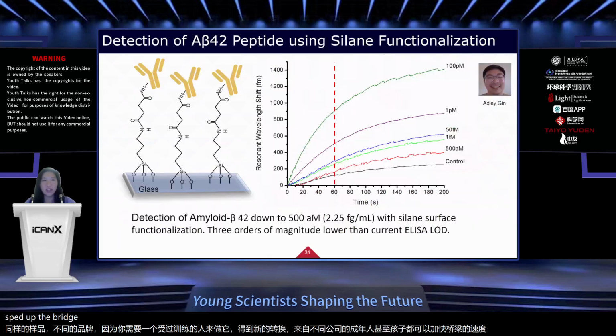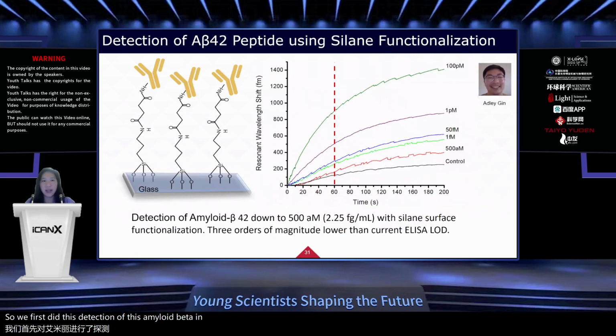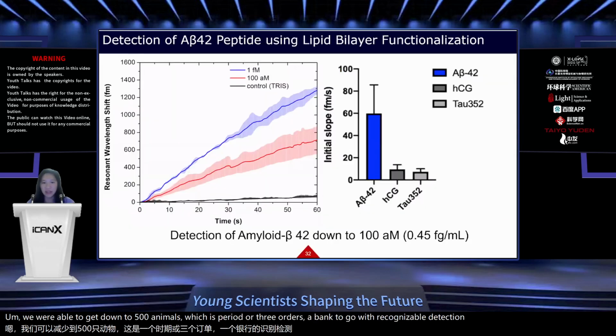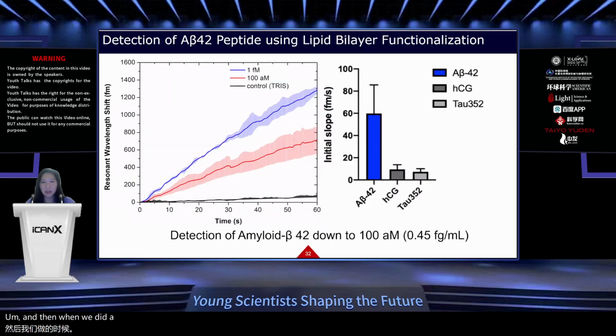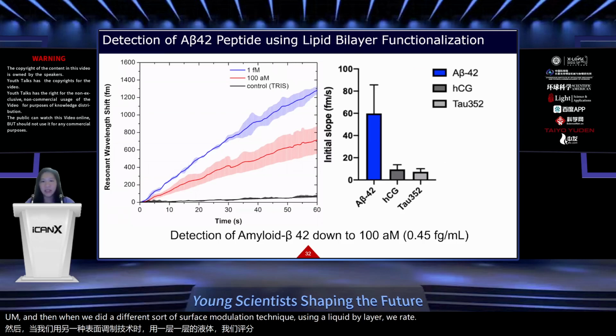So we first did this detection of amyloid beta in pure solution. We were able to get down to 500 attomolar, which was 3 orders of magnitude lower than the current ELISA limit of detection. And then when we did a different sort of surface functionalization technique using a lipid bilayer, we were able to decrease that down to 100 attomolar.